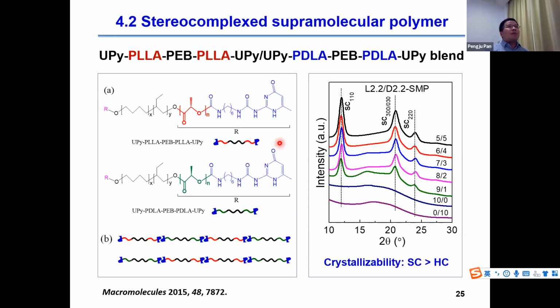Then we mix the supramolecular block polymers containing PLA and PDLA blocks. The supramolecular polymer containing only PLA or PDLA blocks is amorphous and can't crystallize. However, the polymer becomes crystallized when the PLA and PDLA block polymers are mixed. The crystallinity can be controlled by changing the mixing ratio of PLA and PDLA blocks. It increases as the contents of PLA and PDLA blocks become similar. This indicates the stereocomplex crystallization has a higher crystallizability than the homocrystallization in the same condition.